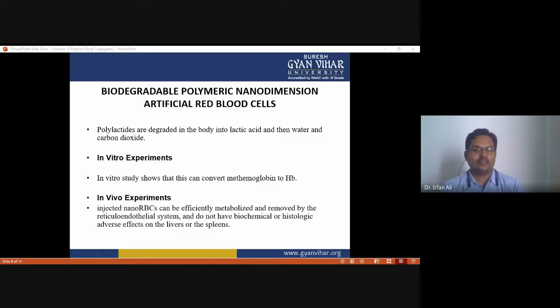And in nano RBC, the biodegradable polymeric membrane can be made permeable to glucose and other molecules, and this allows us to prepare hemoglobin nanocapsules containing the methemoglobin reductase system, in which external glucose can diffuse into the nanocapsule, and products of the reaction can diffuse out and therefore do not accumulate in the nanocapsule and inhibit the reaction.